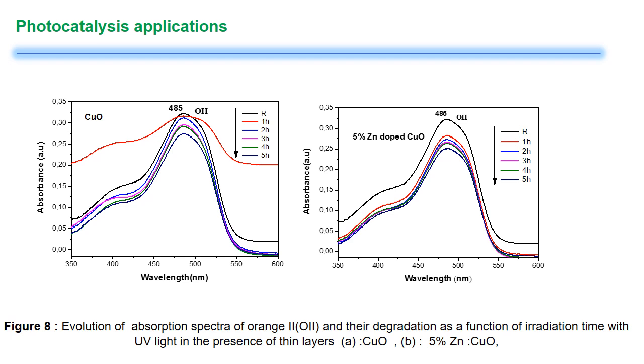The following figure presents the absorption spectra of Orange II (OII) dye in the presence of the films as a function of wavelength. All spectra present the degradation of Orange II over a time between 1 hour and 5 hours. The maximum absorption is at a wavelength of 485 nanometers, which represents the wavelength of Orange II.